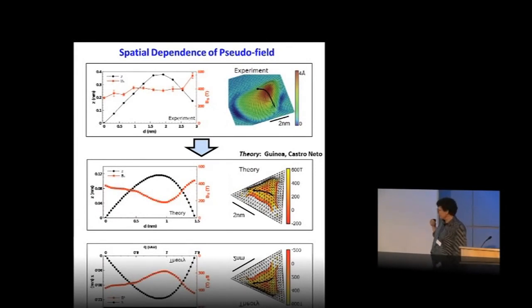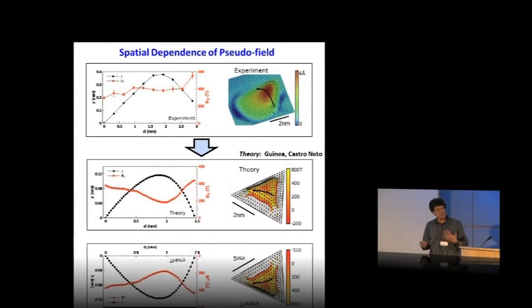And this is a result that I'm very excited about. One of the reasons is because these pseudomagnetic fields are so high, several hundred tesla, it gives us access to a new physical regime. For example, if you consider DC magnetic fields, the largest DC magnetic field that anyone has ever created in a laboratory is less than 100 tesla. But now we're looking at pseudomagnetic fields up at around 400 tesla. So this allows us to potentially explore a physical regime that could never be accessed by any other means.